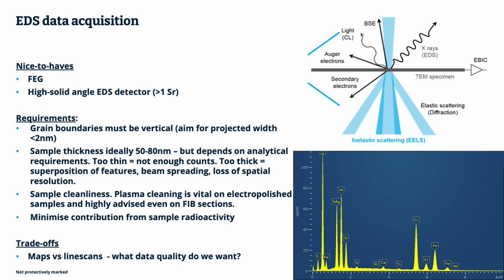To get decent analyses out of a grain boundary, it's not just enough to find a grain boundary. You've got to make sure that it is really well aligned with the beam. If the boundary is twisted, as it inevitably will be if you're going to map a large area, the effect of segregation to the boundary will be diluted in the projected image that you finally see. So making sure that the boundary is properly aligned to the beam is pretty essential.